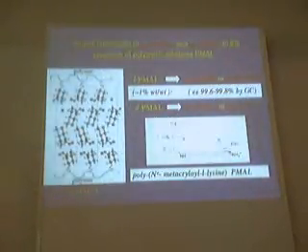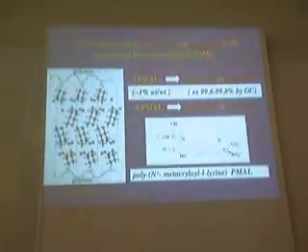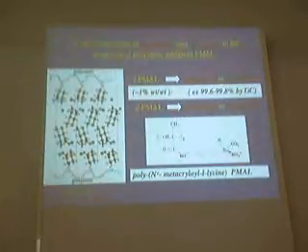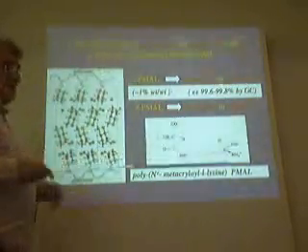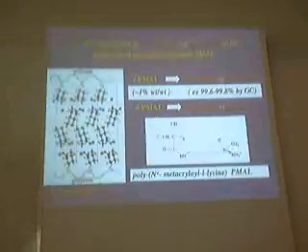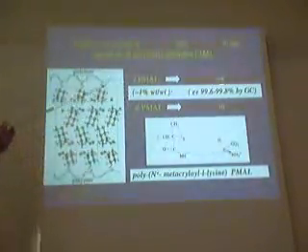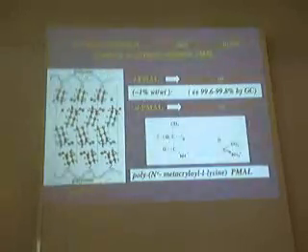And in order to explain that experiment, what we are proposing is that you have clusters in solution. The crystal cannot grow molecule by molecule, but it must grow by cluster. By having this particular molecule, which can be targeted enantioselectively on some specific clusters of the solution, you prevent their growth, and the other one can now grow nicely. And this process has been elaborated on 10 kilograms, actually.